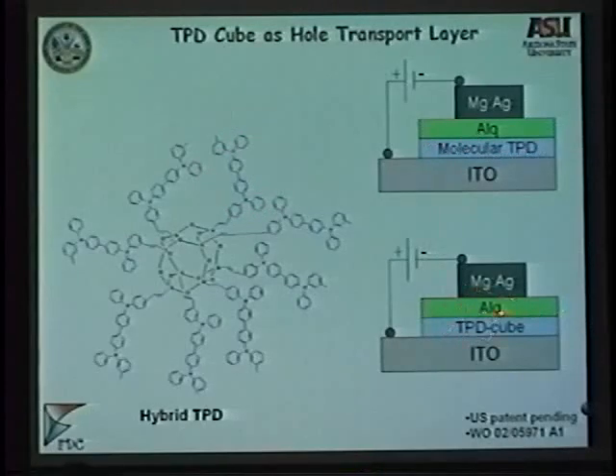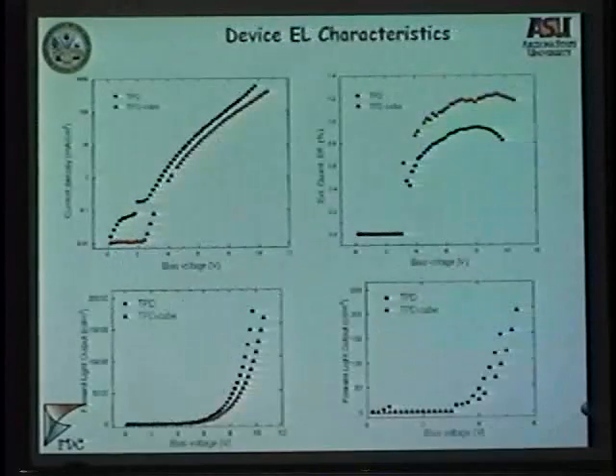Then we evaporated on both substrates about 60 nanometers of aluminum quinolate, which is an electron transporter. It also emits green light. Then we deposited the cathode on both and connected them to the battery. And this is what we saw. The TPD molecular material is in black, and the TPD cube is the red triangle here.